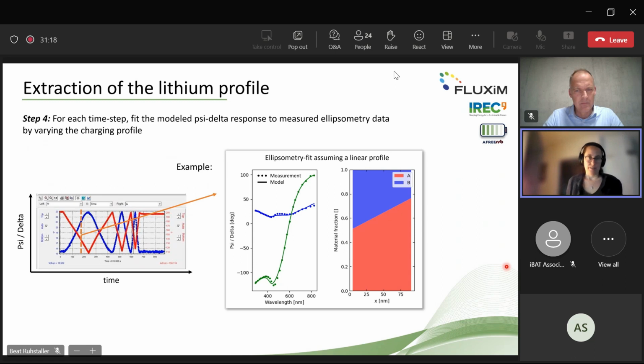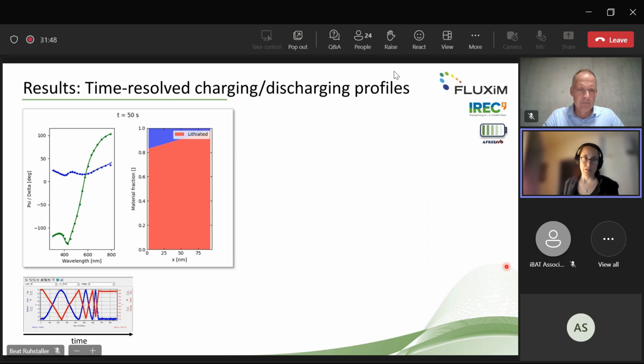Yes. And here is just an example. For each time step, one would then need to do a model where you fit the measured psi and delta with our optical model. And the free parameter is, of course, this ratio x. And here on the right-hand side, you can then see the profile: material A and material B, and there would be this linear profile in this case for this specific time step.